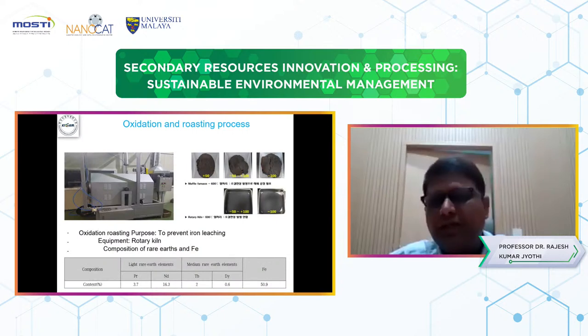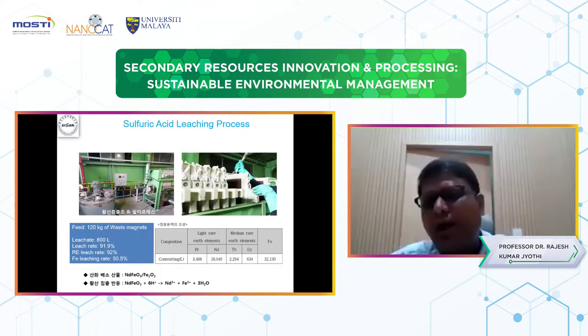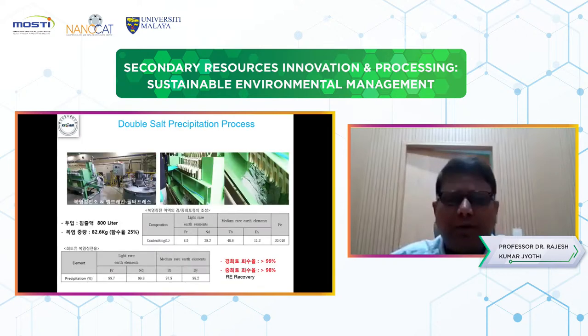This sulfuric acid dissolves almost 32,000 of iron. So to remove the iron, we go for double salt precipitation using sodium bisulfate. Then with the double salt precipitation, rare earths can be recovered at 99 and 98% without iron, with only a negligible amount of iron.